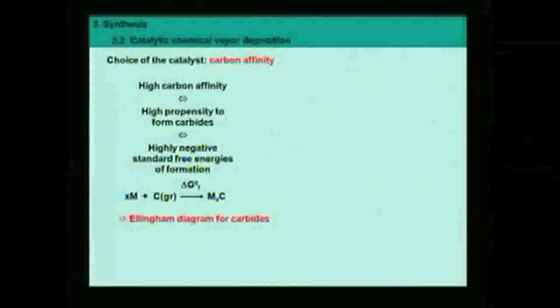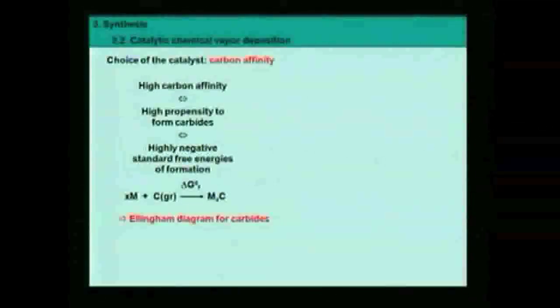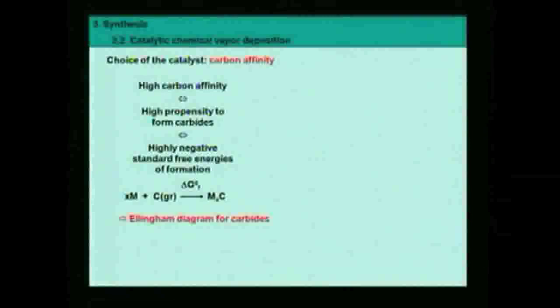Here also we can use an Ellingham diagram for that. We can plot the free energy of formation of carbides for different elements. And the definition of this free energy of formation is given here. It's the free energy for this reaction between the metal, the carbon considered as graphite, and the carbide formed with this metal.